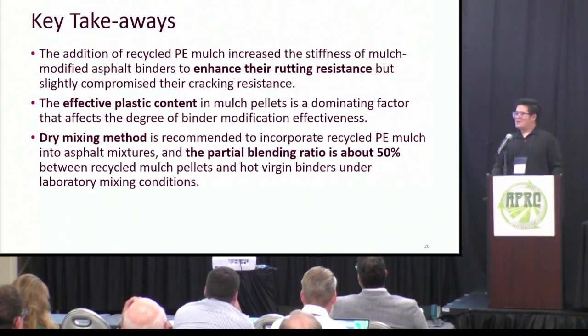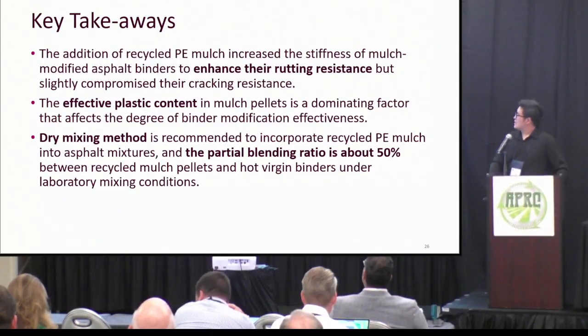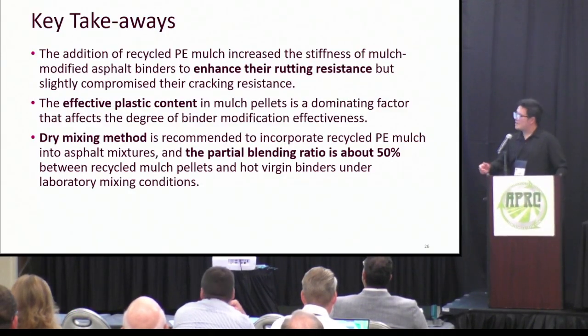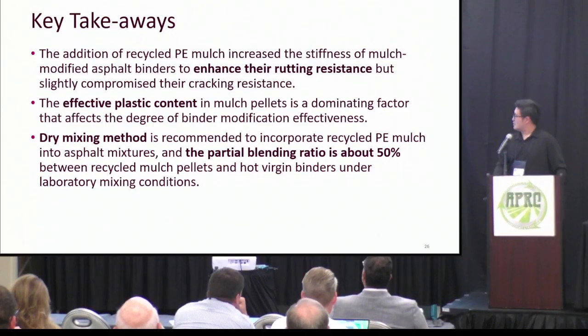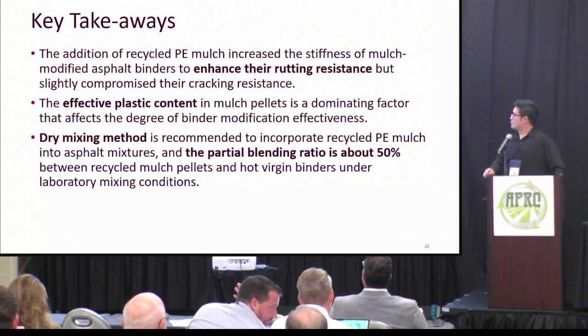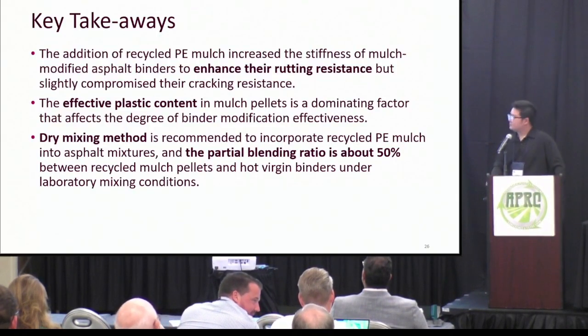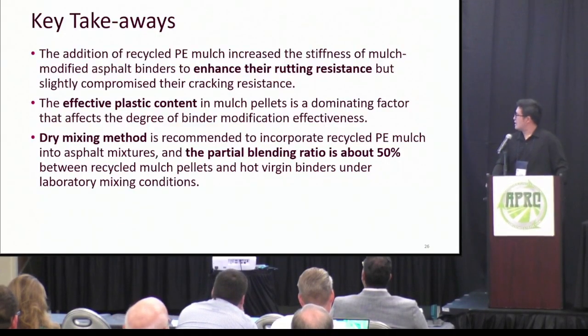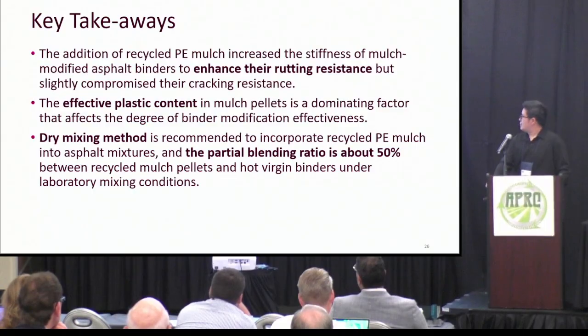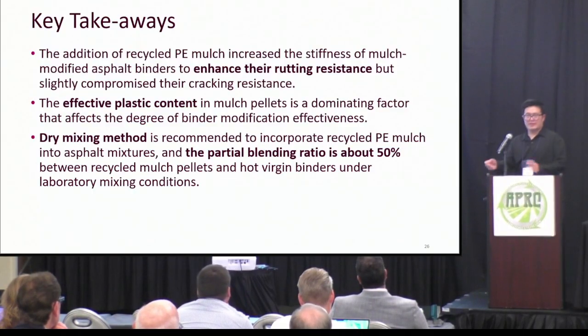And finally, let's see the summary here. The addition of recycled PE mulch increases the stiffness and benefits the rutting resistance, but slightly compromises the cracking resistance. Also the effective plastic content is a dominating factor that affects the degree of binder modification. The third is that the dry mixing method is recommended to incorporate recycled PE mulch into asphalt mixture, and the partial blending rate during the dry mix method is around 50%.